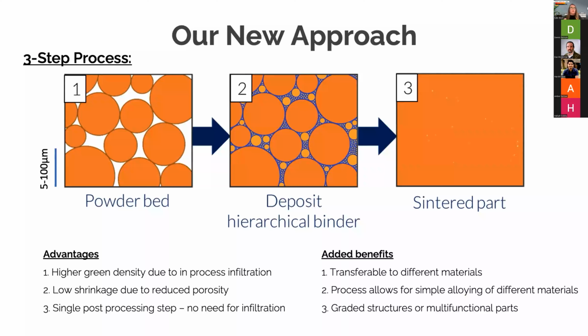But then, due to the additional components that we're adding to that binder, it enables us much greater flexibility as to what materials they could be. In this particular case, we see on the slide here, we're using copper, but imagine if that powder bed was one material, the microparticles held within the binder are another, the nanoparticles are another, and then the reactive organometallic is another. We can start to see how these would be transferable to different material systems. But also we could start to see for the very first time graded material structures or graded multifunctionality across that 3D geometry. So we've mitigated the risk of porosity or high porosity in parts.